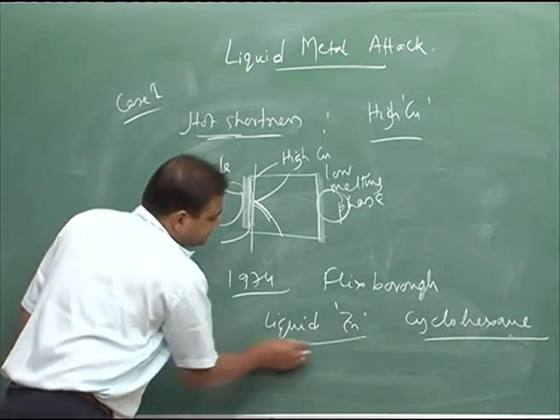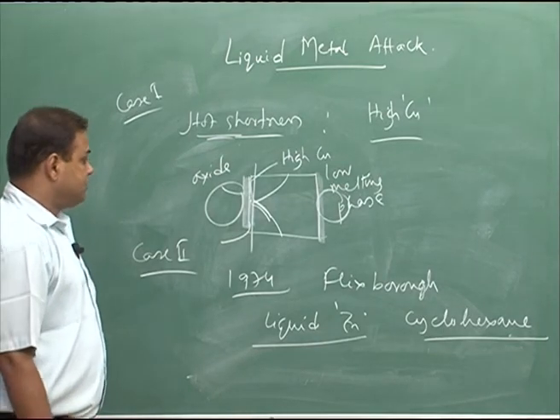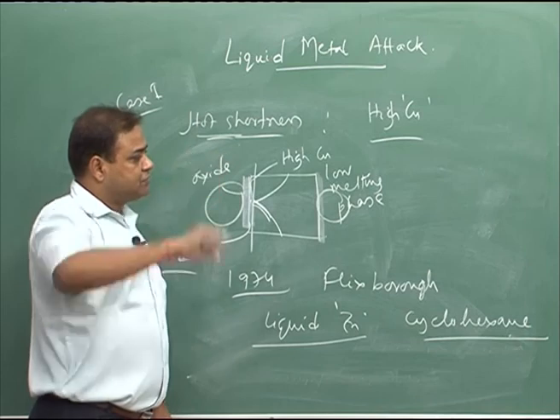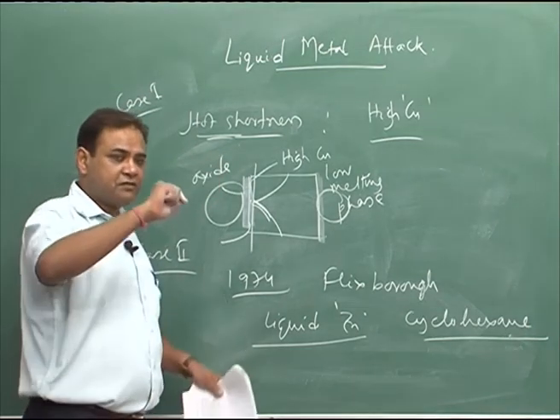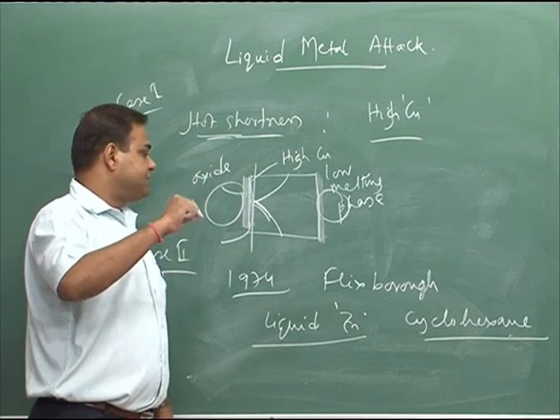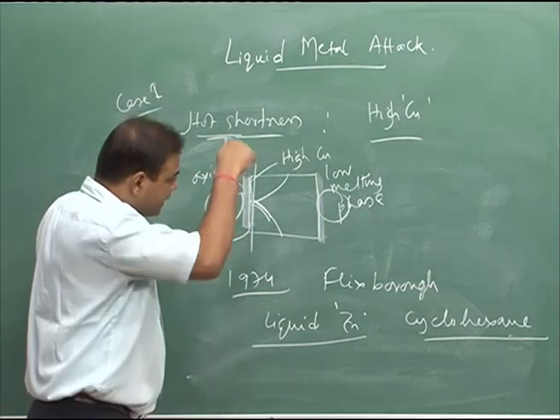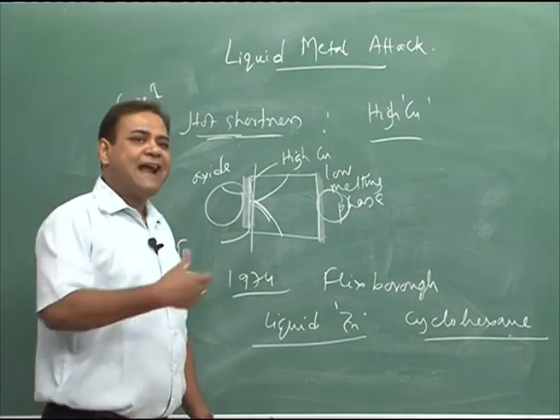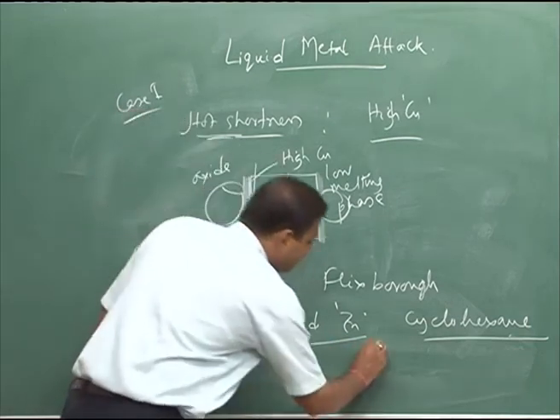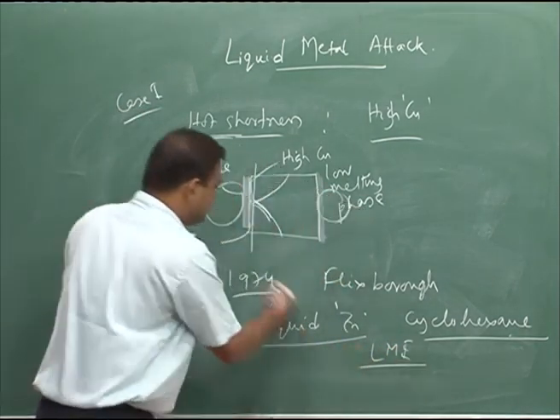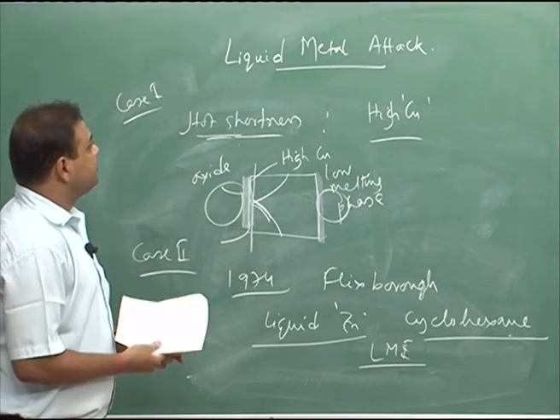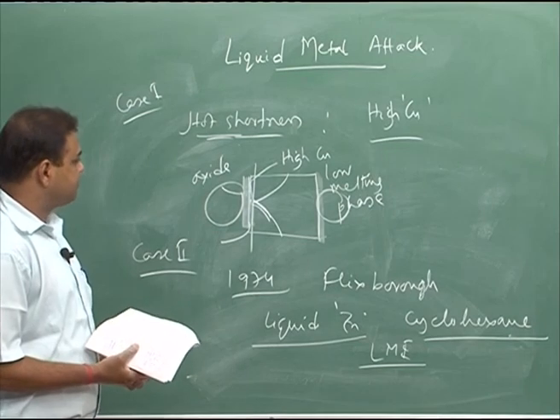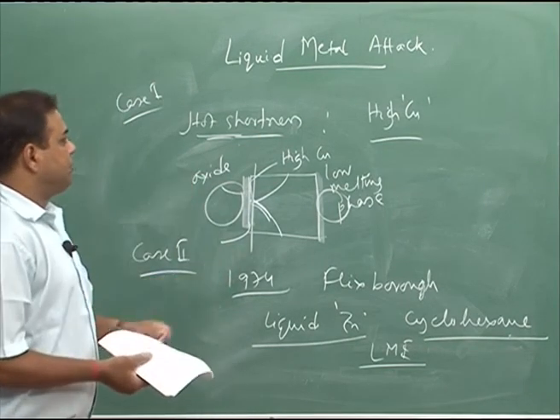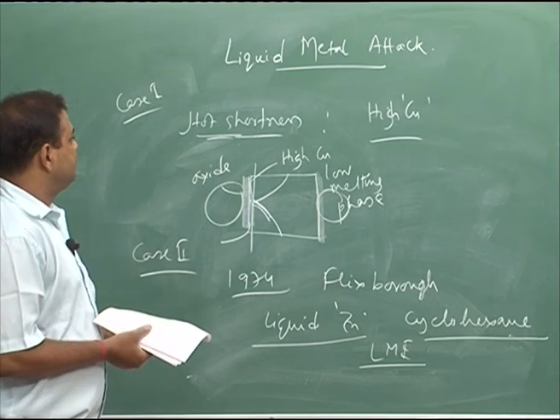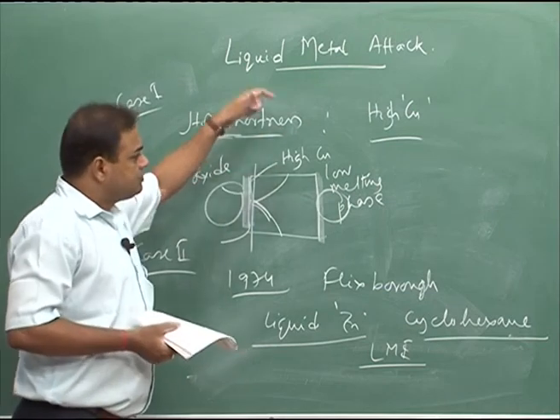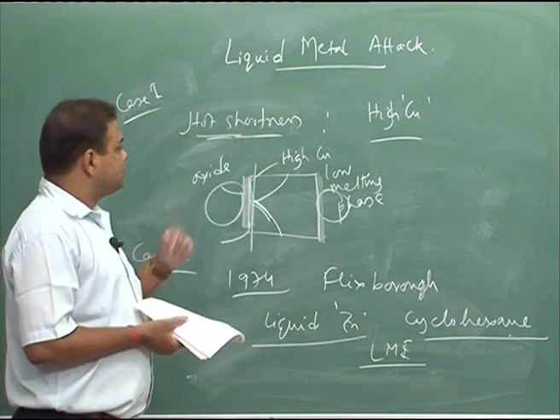And there the source of that liquid zinc was that in that factory they used galvanized staircases, and due to the heat, the zinc droplet fell on that pipeline, and that led to liquid metal embrittlement of that pipeline. So, this is another example. That means the liquid metal embrittlement can be fatal in some cases. So, this is about liquid metal related attack, and more specifically the effect of embrittlement due to the presence of liquid metal.